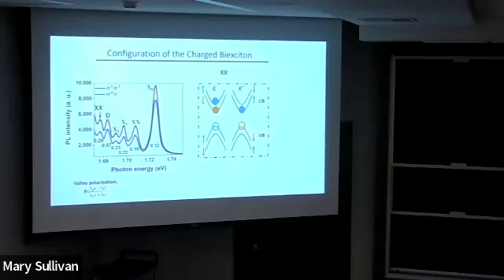Normally there's an optical component, there's a spin component. Additionally, there's a valley degree of freedom. If you compare bright and dark, let's say I compare dark and bright, this one has the same value. So the valley phase is the same, but the conduction band is the opposite, right? So that will differ by roughly 2 or 4 already. And then you can consider the conduction band. If you go through the calculation, that's 10 instead of 4.